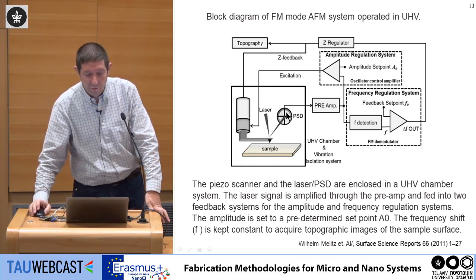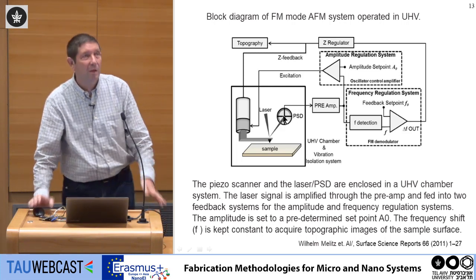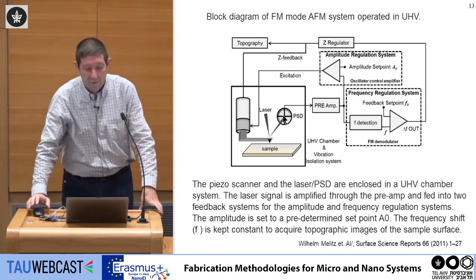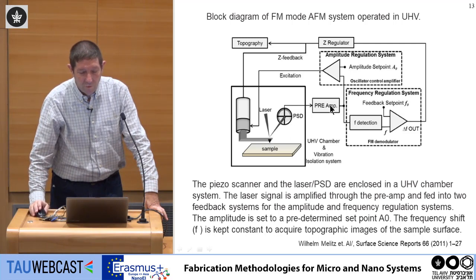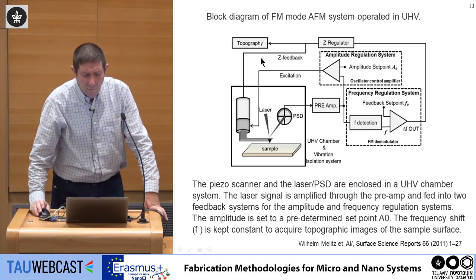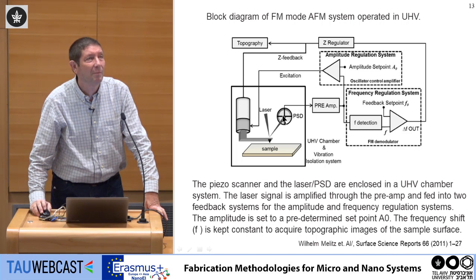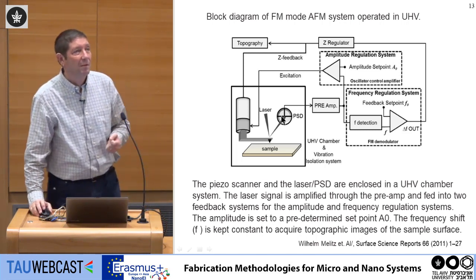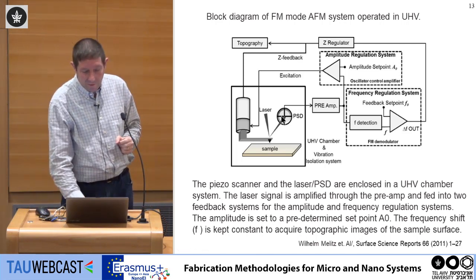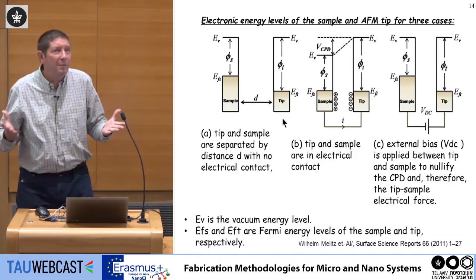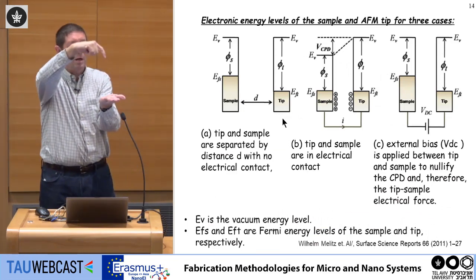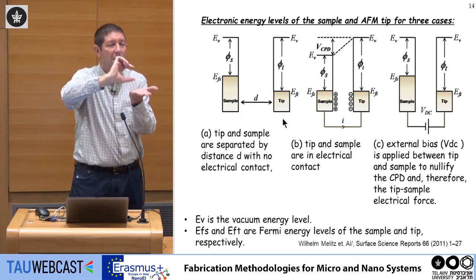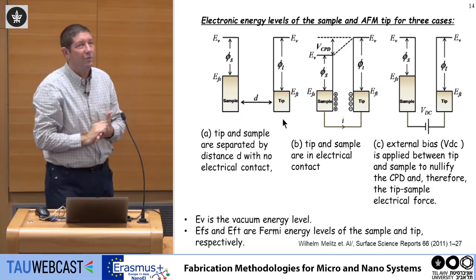But if the light is going from here to the center to here, this photodiode generates a larger signal, and this photodiode a lower signal. So by using this method, you can identify the motion of the tip, and you translate it to a signal through the preamplifier. Then you take the signal out, and you apply a feedback signal that you want to maintain on the same place. Maintaining the same place means the same force, which means the same distance. Now, this is a very simple principle. You apply a tip, and if it's going up and going down, you try to maintain a fixed force between the surface and the tip.